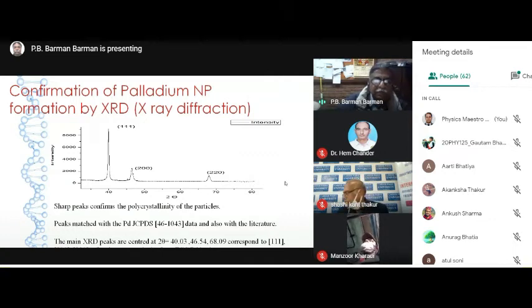So after this palladium nanoparticle has been formed, we went for XRD, and we can see it practically matches with the various peaks, confirming that this is a polycrystalline particle. Secondly, you can also see this 111 peak, which is more intense. We'll talk about this one, as it will help us identify the sensing property of my palladium. So this is the peak to be matched.